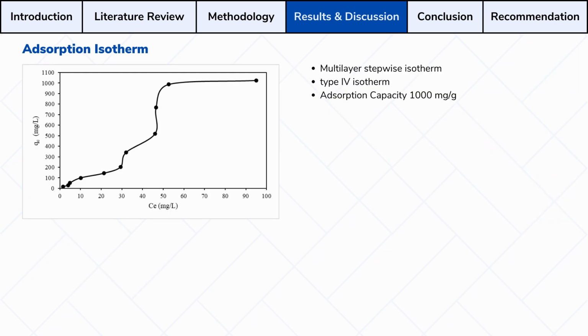The manifestation of a step-like isotherm, particularly when organic compounds are adsorbed, arises from cooperation and interaction among the adsorbed molecules. Multilayer stepwise isotherms, categorized as Type IV isotherms, have more than one inflection point and local maximum, presumably due to the non-monolayer nature of adsorption. The isotherm shape suggests a potential change in adsorption interaction, possibly related to the formation of multilayers of dye molecules.